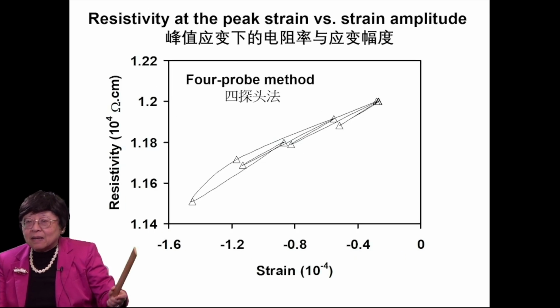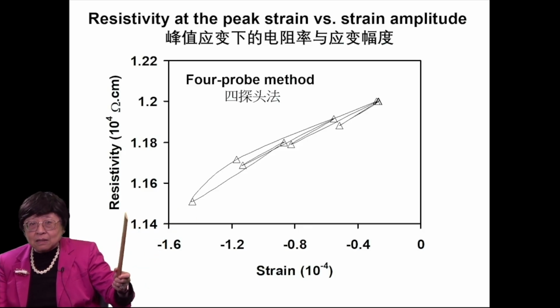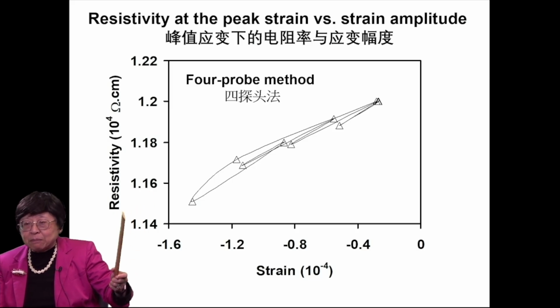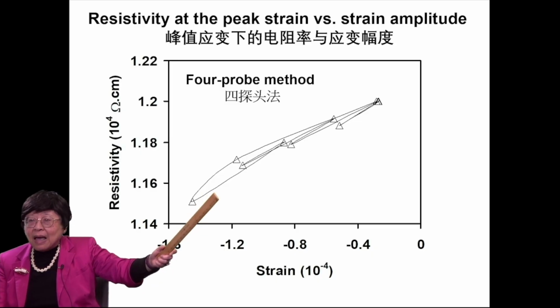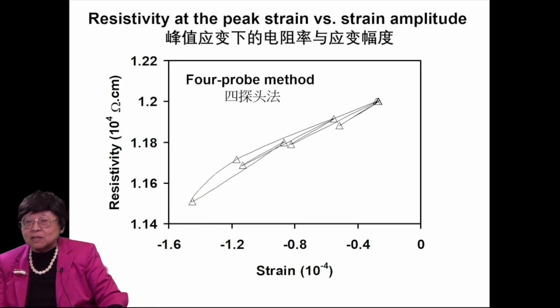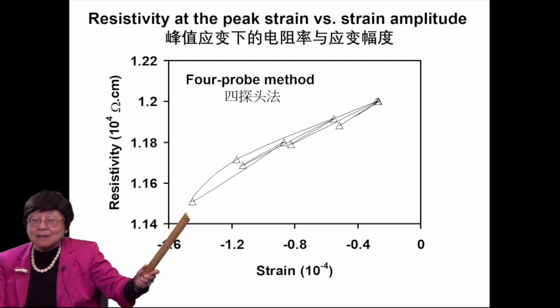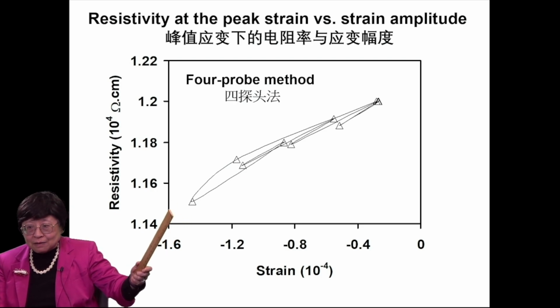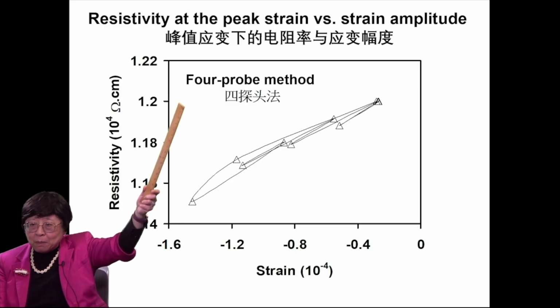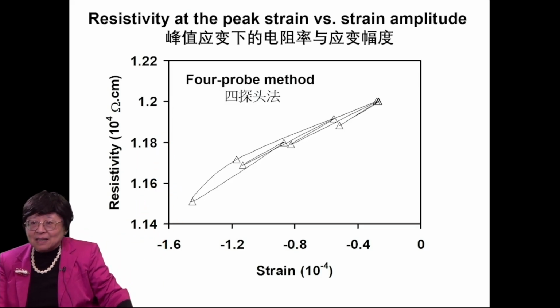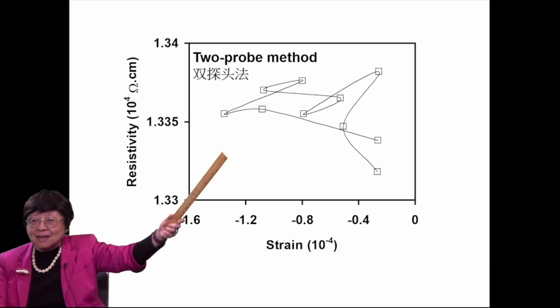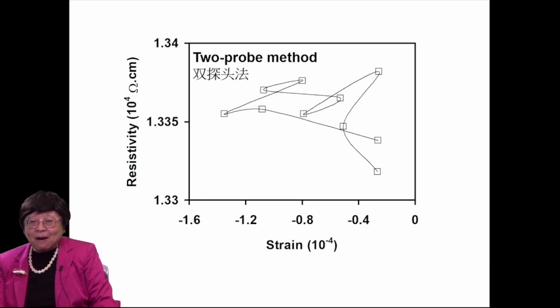And we can plot the resistivity at the peak of the strain at each strain amplitude versus the strain amplitude, and connect the various data points chronologically. And one finds that it's more or less linear, not too much hysteresis, so that's good. This is obtained using the 4-probe method. But instead, if one uses the 2-probe method, it's terrible. And that's why the 2-probe method is really unreliable.